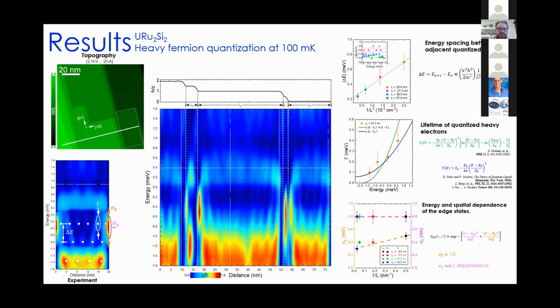Doing this analysis, we complement the plot that I showed you at the beginning with the values from the other terraces, and we observed that the energy spacing between adjacent levels is proportional to 1 over L squared, which is consistent with the quadratic band dispersion that we have. Also, the energy and the spatial dependence of the edge states as a function of the terrace width is plotted here. We observe that in energy, the width of the edge states is inversely proportional to L, where L is the width of the terrace. And the width as a function of distance doesn't have L dependence.